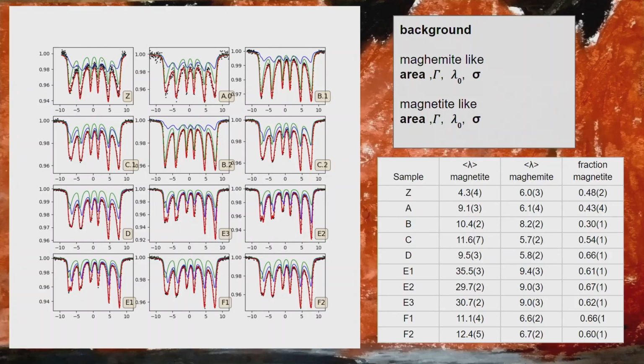In this fit, the parameters are the background, the area of the maghemite, and gamma of each site, the same gamma. Each contribution of each maghemite sextet has the same gamma. The lambda 0 and sigma are the parameters of the log normal. Log normal used to have two parameters, and from these two parameters you can calculate the mean lambda, like the mean volume. So we are able to have mean lambda for magnetite, mean lambda for maghemite, and also, because of the areas, mean fractions.